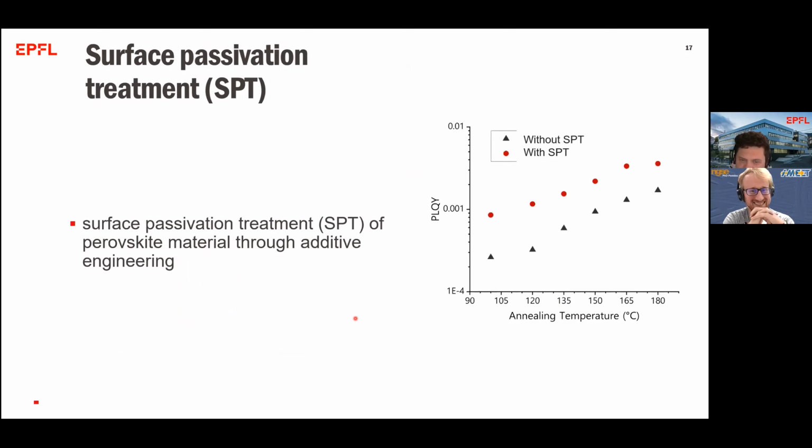It's a tiny additive in the second step, and it does the following. It helps us with passivation. So we see that the temperature helps, but then even above that, adding this additive increases the photoluminescence efficiency and thereby the potential open circuit voltage of the whole system.